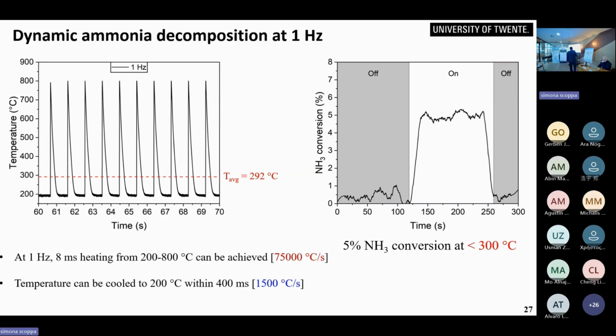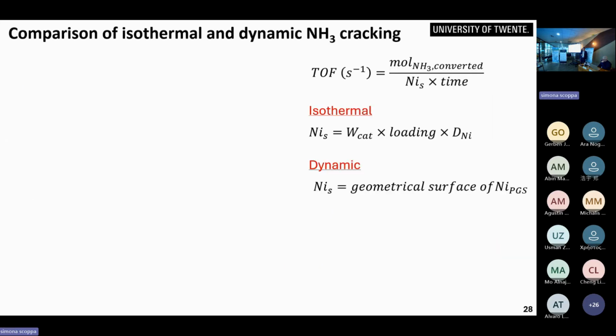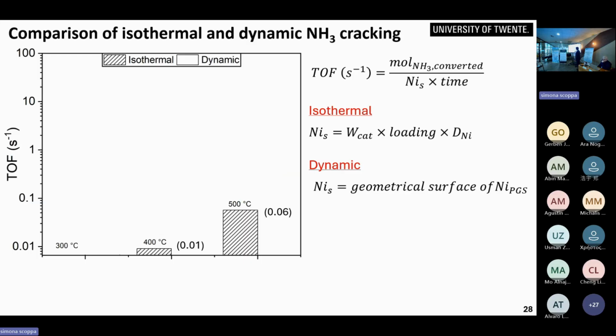You might wonder, what exactly does this mean in the context of ammonia cracking? Well, we can calculate a turnover frequency assuming the geometrical area of nickel that is available for this reaction. To benchmark these results, we have a separate plug flow reactor where we have tested nickel-based catalysts on alumina. These are the typical turnover frequencies that we get, which are in line with a lot of the literature. You get values of 0.06 seconds to the -1 at 500 degrees C.